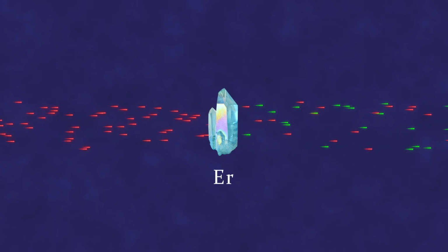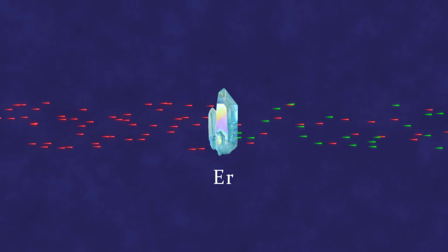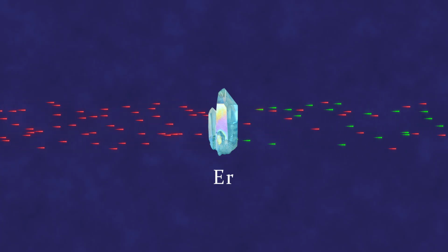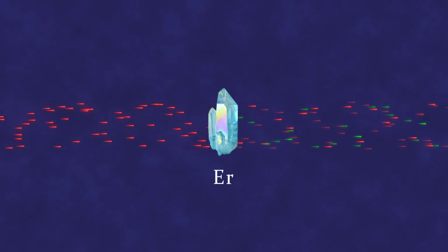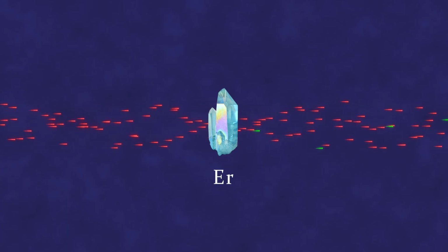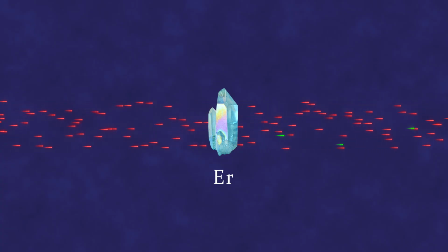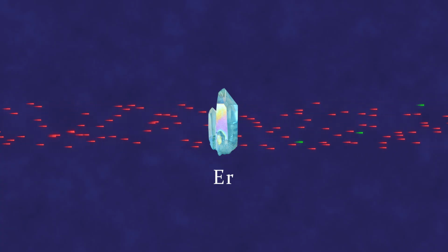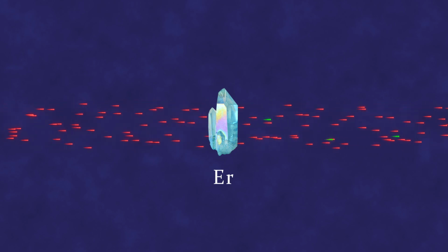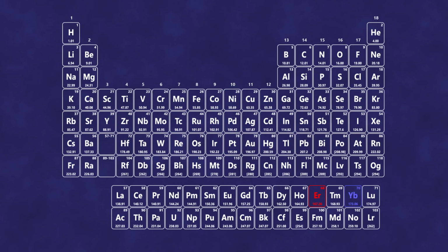In practice, it turns out to be a bit more complicated. Erbium is quite reluctant to absorb infrared radiation with a wavelength of 980 nanometers. Erbium atoms absorb only a tiny fraction of the incoming stream of infrared photons, and the chance that such absorption will happen twice in a row during the 50 microseconds that erbium lives in the excited state 4I11/2 is nearly zero. A relatively good absorber of photons with a wavelength of 980 nanometers is a relative of erbium, ytterbium.